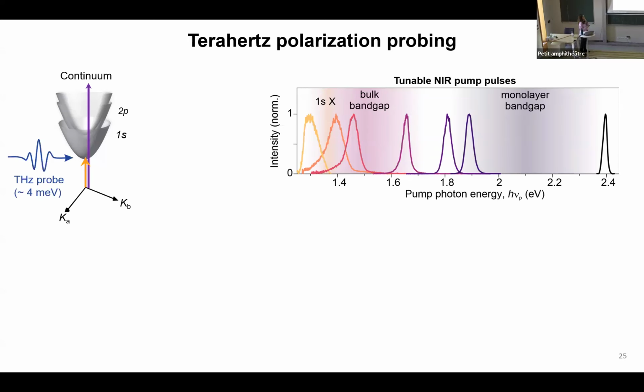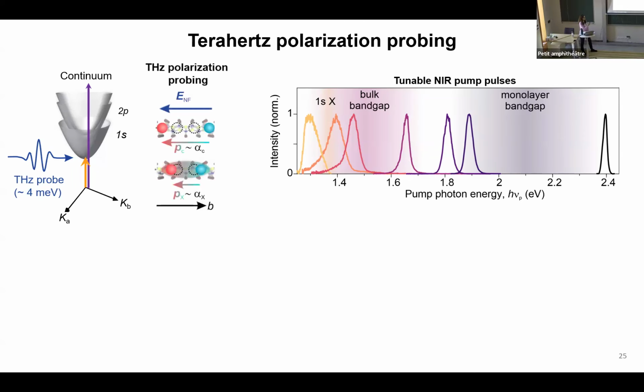Now this time we come with terahertz radiation. A terahertz pulse is a pulse whose energy is about a few milli-electron volts. 1 terahertz is about 4 milli-electron volts. This energy regime is too small to excite excitons from the 1s state to the 2p state, because remember, that was about a few tens of milli-electron volts, as we saw in the bulk. However, when we shine the terahertz light on pump-induced free electron and hole pairs or excitons, the instantaneous electric field of light will have an effect on these electron and hole pairs. It will induce a dipole moment in the electron and hole pairs, and therefore the terahertz radiation can probe the polarizability of this species.